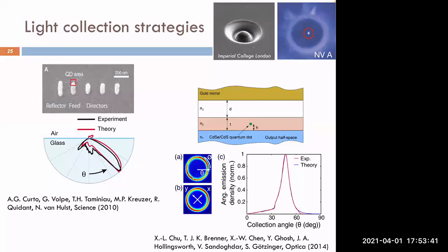And secondly, diamond has a high refractive index. So the light likes to stay in diamond because of the total internal reflection that probably you studied when you went for Snell's law in physics courses. So people have worked a lot in this direction. So people created solid immersion lenses, as you can see here, this picture from Imperial College, to get better emission from the color center. In other case, people work with nanoparticles. So here you see the example of a Yagi-Uda antenna created using gold nanorods. And this was applied to quantum dot, not to color centers.